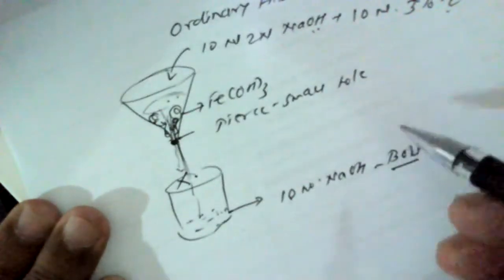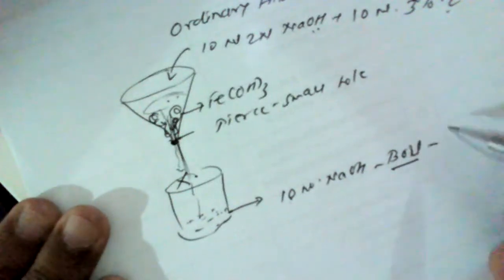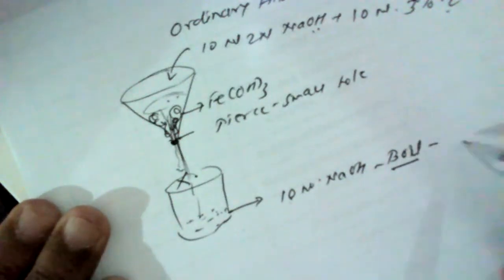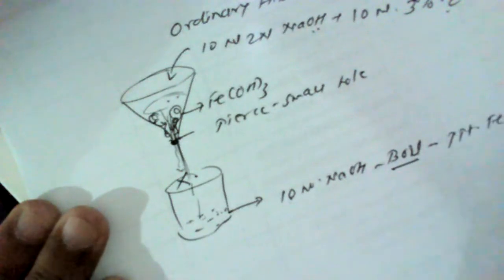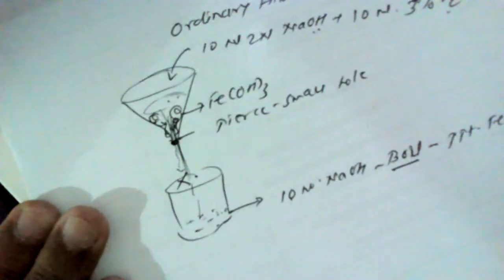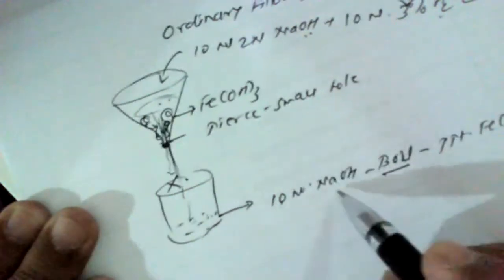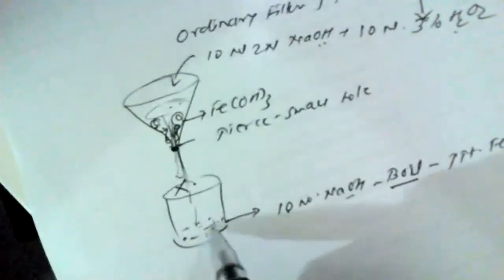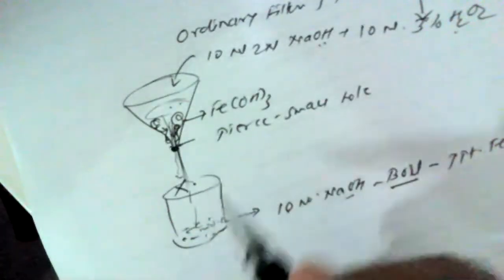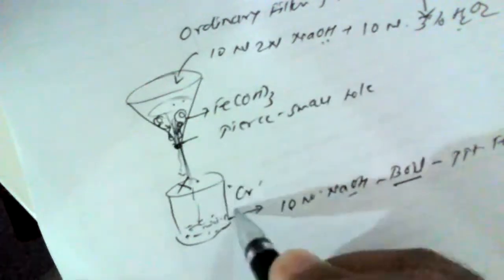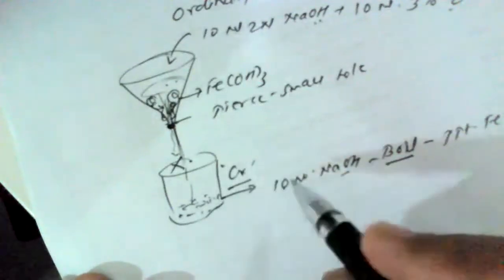Now, when we boil this beaker, the precipitate of ferric hydroxide remains undissolved. That means no effect takes place substantially by adding this NaOH solution. So we have obtained here ferric hydroxide in an undissolved condition, which contains also chromium in addition to iron. Now we have to separate chromium from iron.